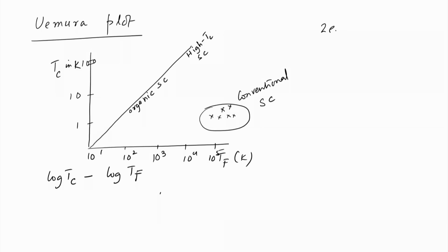So, the unconventional superconductors still have Cooper pairs as their most important constituents. So, there is a 2e charge that needs to be seen, and as we have seen earlier, the 2e charge is confirmed from the flux quantization measurement, and the value that we get is around 2 into 10 to the power minus 15 Tesla meter square. It is a small value, but it still confirms that one needs a 2e charge in order to get the flux quantum to have this value, which is verified in experiment.